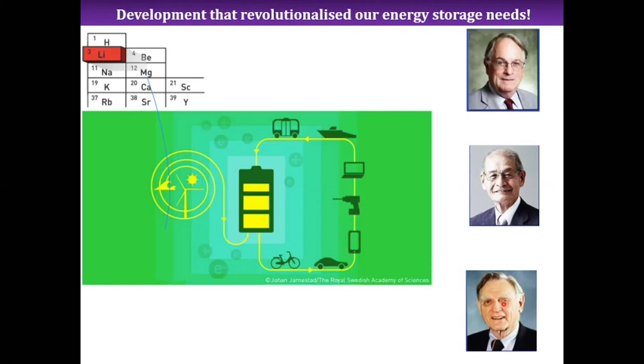Then came Goodenough. This man gave the idea of lithium cobalt oxide, which is a more stable form, and that could actually host the lithium in more space. It could provide more space than titanium disulfide. And since lithium cobalt oxide has lithium already present in the system, that gave a solid framework for lithium to intercalate and deintercalate. So this is how the convenience started with a rechargeable system.